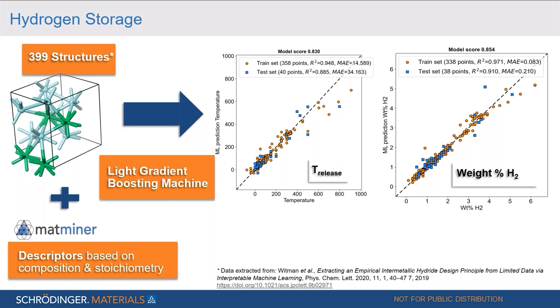So what one can do is, machine learning approaches can be very useful in predicting the performance of these potential materials for hydrogen storage in case there are data available which can be used to train the models. In this example, there were data, so the 399 structures from the Witman dataset were extracted, and models were built for the release temperature and the weight percentage of hydrogen. And we see here that for both properties, we get again a good agreement between observed and the predicted property. For both, the R-square value is rather high in both cases, for the training set and the test set. So these two properties could be predicted very well using machine learning.